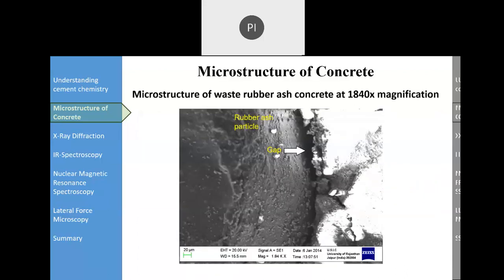Again, very interesting, here this is our laboratory study, we try to use waste rubber ash in concrete, and then we try to see what's happening at the interface level, which is the weakest part. So this is the rubber ash particle, and this is like sort of aggregate, and this is a clearly visible gap between the aggregate and the rubber ash particle.